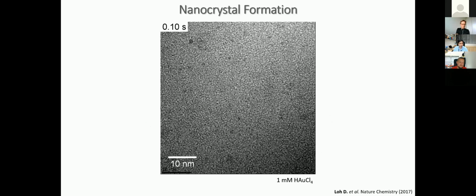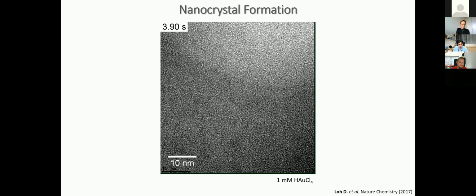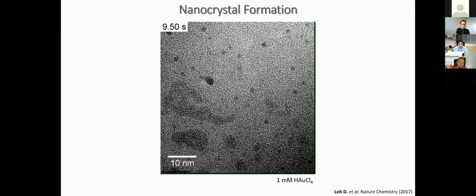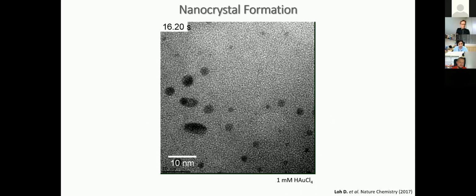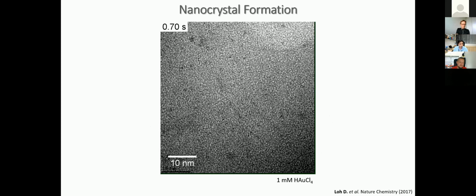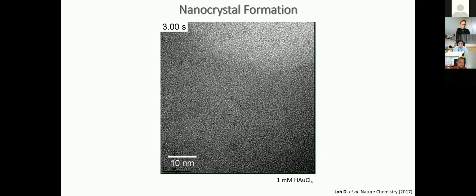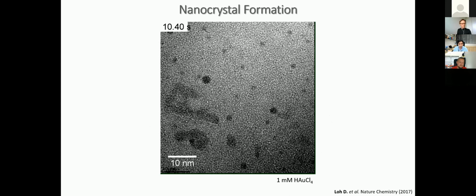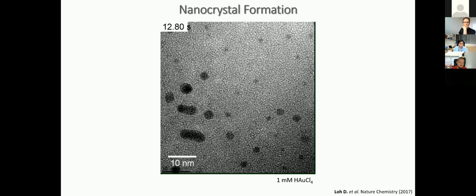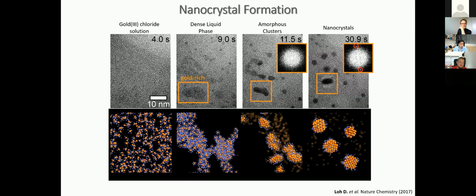Here what you see is the nucleation of gold nanocrystals imaged with a TEM from a solution. You have a gold precursor solution that just has gold ions, and while you're imaging, you see how the gold phase is emerging. This is one of our earlier works. If you break down the movie into pieces, you start with a homogeneous precursor solution. The solution phase separates into gold-dense and gold-poor regions. These dark regions are gold-dense or solute-rich regions, and the brighter regions are the solute-poor regions.